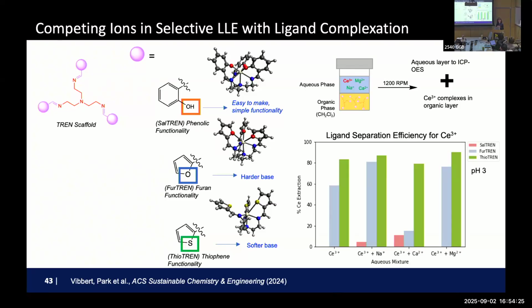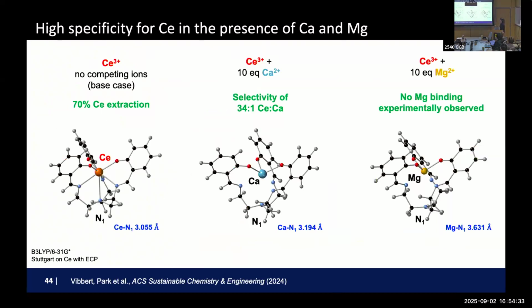We were able to somehow grab onto cerium in the presence of a whole bunch of other ions surrounding it. The reason was, this is our DFT calculation, because of the tiny size difference, the cerium was really snug in all 7 binding sites compared to calcium and magnesium. It doesn't bind to all the sites. So it was kind of bouncing in and out of that space so that we were able to capture only